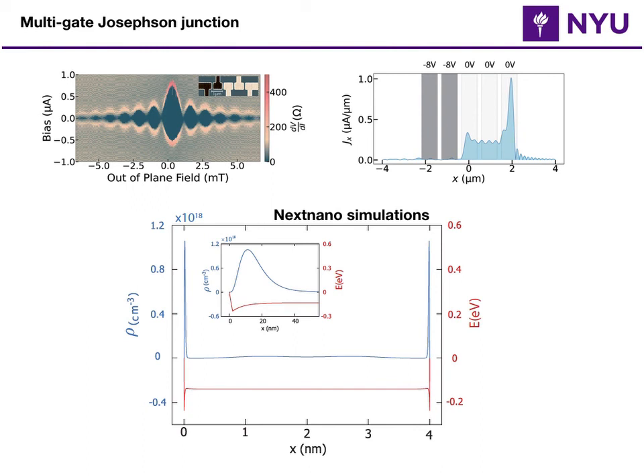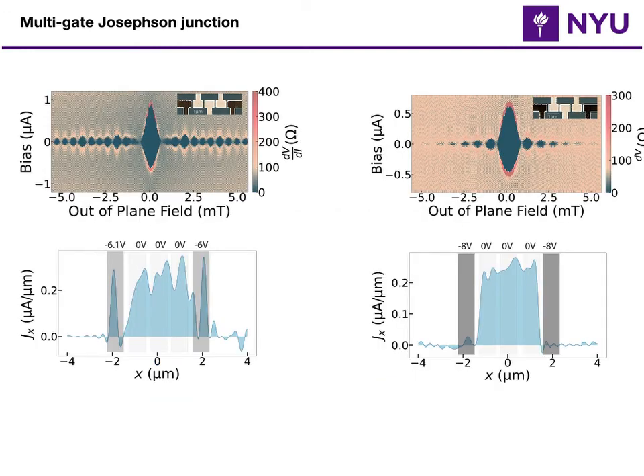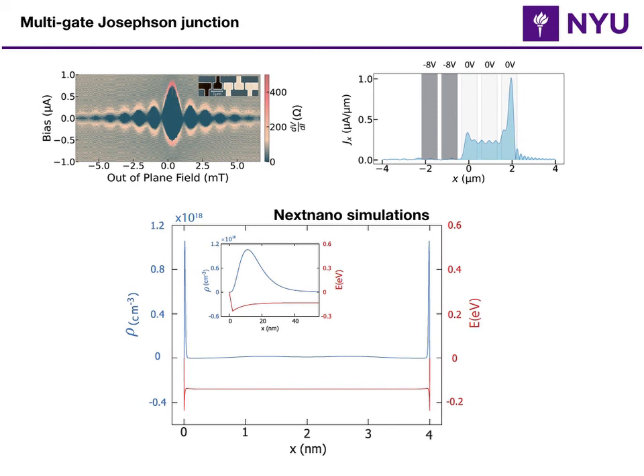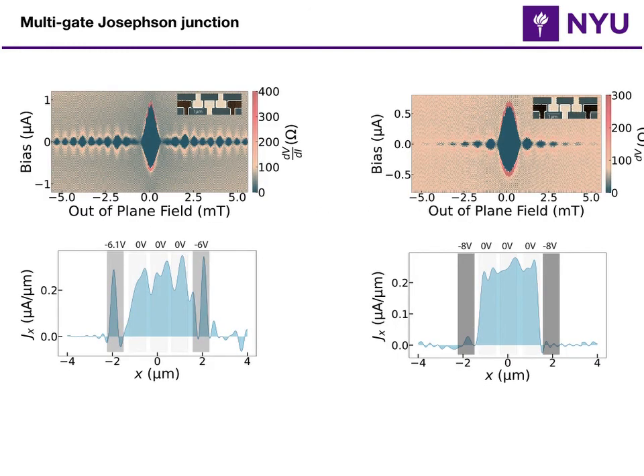So we thought first maybe we can make a uniform current distribution by lowering the gate, not depleting the end gates, but just lowering the gates just enough that their height is the same as the rest of the middle gates. And that's what is shown on the left side. And you see the peaks on the ends, at -6 volt and -6.1, have brought the peak into the right range, but the connection between these and the middle part is basically missed, right? It goes to 0 and then it comes back up. This is very consistent with this picture of surface Fermi level band bending, because that whole band bending effect is at most like 50 nanometers, right? Our mini gates are about 800 nanometers. So by the time we try to balance that edge transport to the right value, we have probably depleted everything else next to it, right?